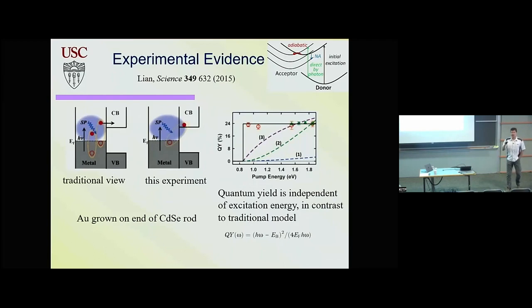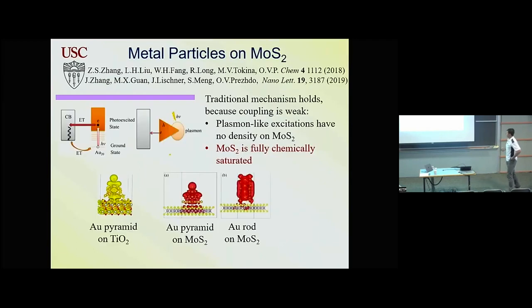And what he did in this case, he grew metallic particles on a semiconducting nanorod. So the connection was also very strong. You had very strong chemical coupling, chemical bonding between the metal and the semiconductor, and this creates the possibility of exciting a charge-separated state. Subsequently, we looked at the same kind of systems on 2D materials, and 2D materials are different